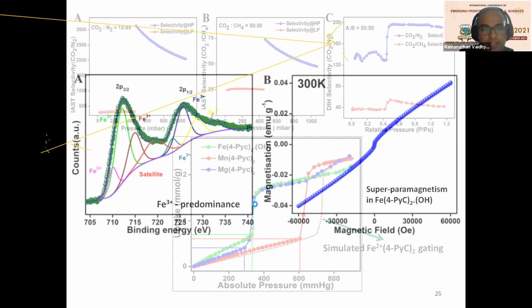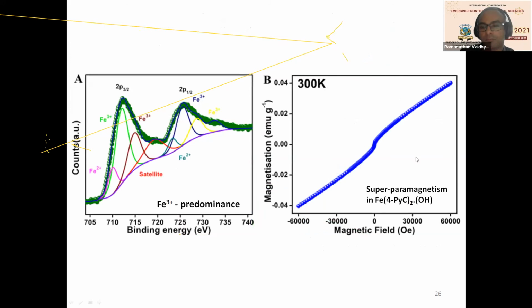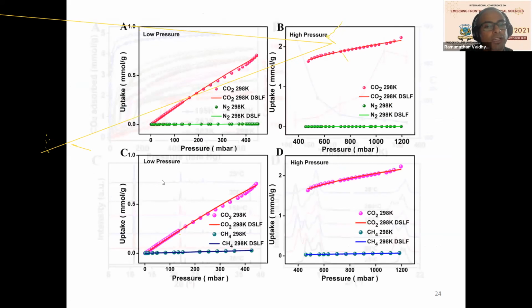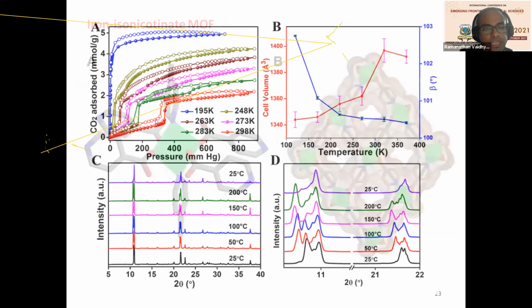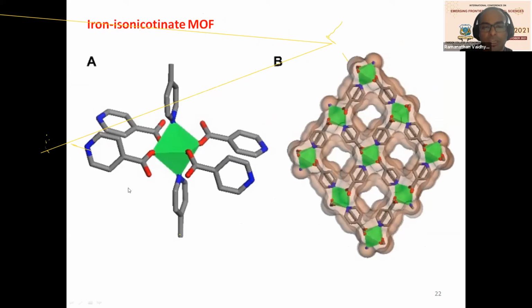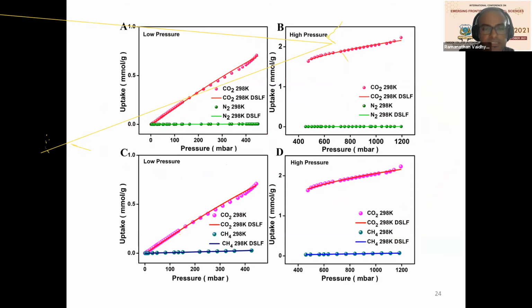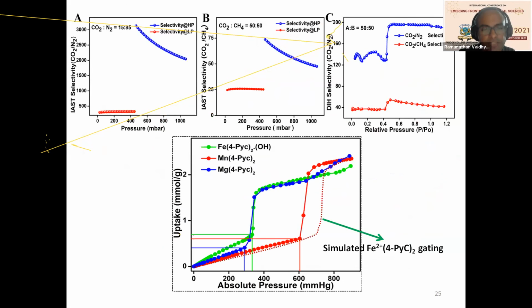Then we did XPS as well as magnetism measurements, and these two show us the sample is rich in Fe3+, not Fe2+. And the beauty is, both Fe3+ as well as Fe2+ can take this octahedral geometry with equal ease, though Fe3+ has a slightly better propensity for octahedral geometry compared to Fe2+. Fe3+ usually takes it very easily. You understand? So the Fe3+ is what we have in the sample. Then we had to revisit our single crystal structure based on this analysis.